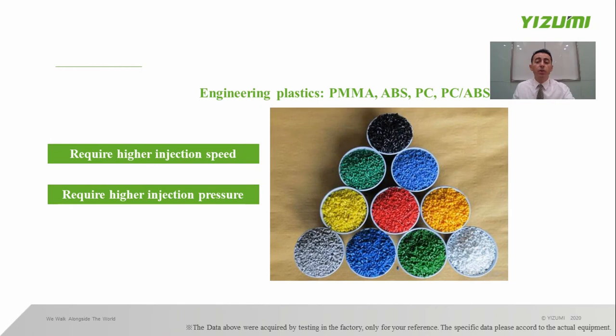Furthermore, as engineering plastics such as PMMA and PC are usually used in IMD products, these materials require high injection speed from the equipment to achieve easy molding. Inadequate speed or pressure will cause failure in molding and the production yield will decrease significantly.